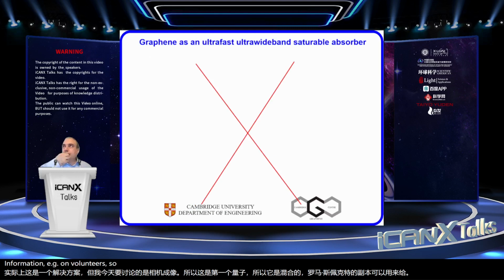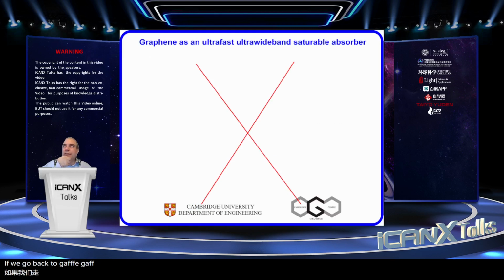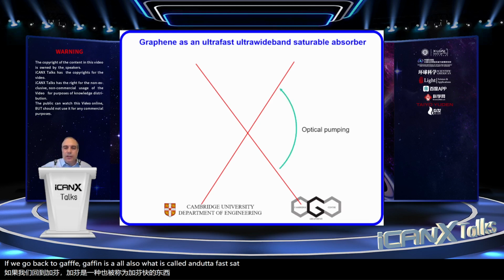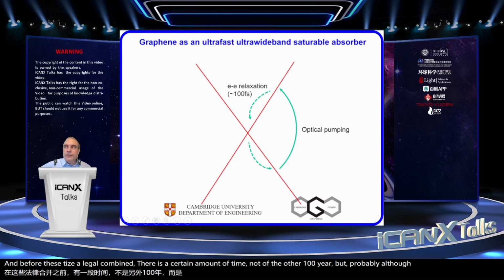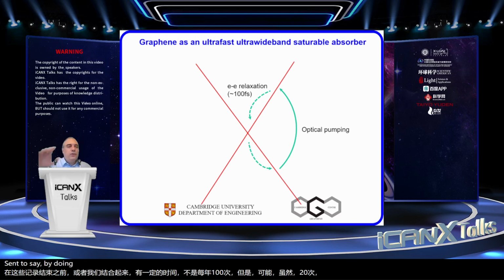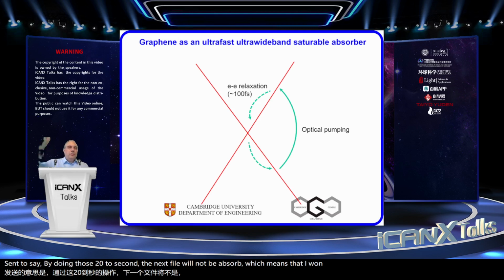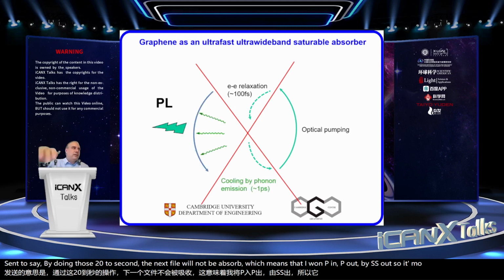So if we go back to graphene, it is also what is called an ultra-fast saturable absorber. If we pump graphene with an ultra-fast pulse, we are now bringing the electrons in the excited state, and before these thermalize or recombine, there is a certain amount of time, not of the order of 100 as here, but probably of the order of 20 femtoseconds. But during those 20 femtoseconds, the next pulse will not be absorbed, which means that I have one pulse in, pulse out, pulse in and out, so it's modulating the light.